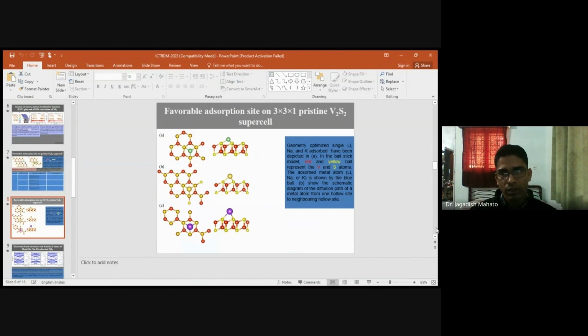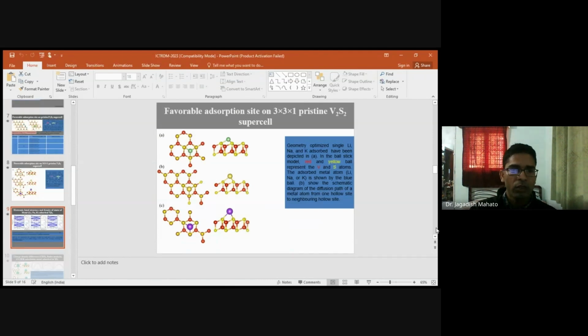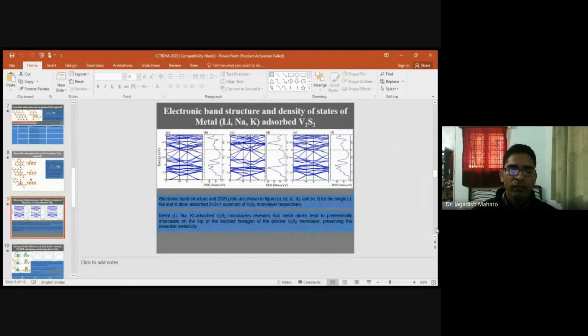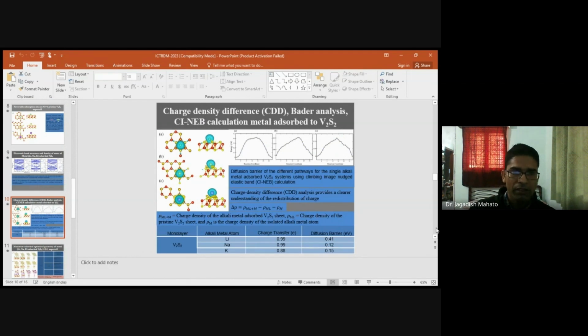After the adsorption of the metal, we can see that the hexagon above which it is adsorbed is a little bit distorted. So it is okay. We then calculate the electronic band structure of the metal atom adsorbed V2S2 sheet, and we see that the sheet retains its metallicity, and in fact the metallicity has increased. We can see from the density of state plot that its value is increased. After the electronic band structure calculation, we calculate the charge density difference to get an idea about the electron transfer from the adsorbed metal to the sheet.